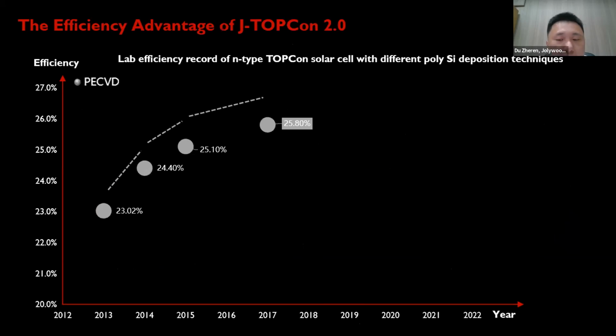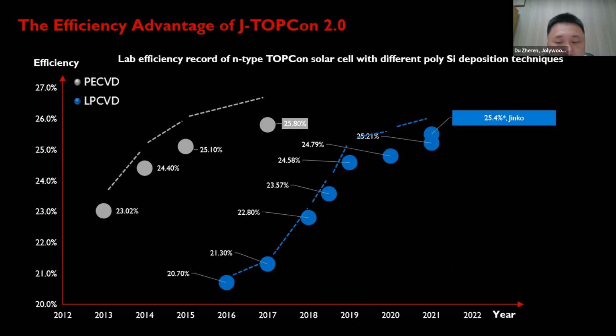We also summarized efficiency records on N-type TOPCon solar cell with different polysilicon deposition technologies. The TOPCon with PECVD technology was first developed in 2013. The highest efficiency so far is 25.8% reported by Fraunhofer 2 years ago, and for the TOPCon with LPCVD technology, Jinko has reported 25.4% on large area cell this year.